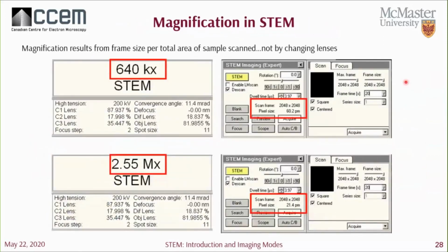What is unique to imaging with a probe, which is also true of SEM, is that magnification results from the area of scanning that is performed on your sample. So magnification is calculated by taking the area of your frame size, say you have a 2048 by 2048 frame, and dividing that by the sample area that is actually scanned. So if you scan a smaller area on your sample with the same frame size, then you're increasing the magnification of your image.